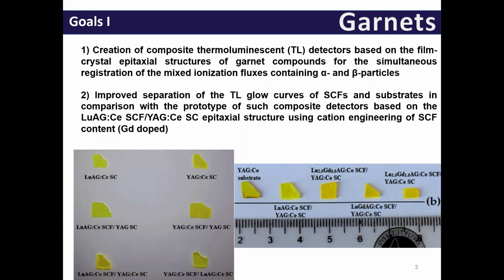The first part is about garnets. The goals are creation of composite thermoluminescent detectors based on the film crystal epitaxial structures of garnet compounds for the simultaneous registration of mixed ionizing fluxes containing alpha and beta particles. And the second goal is improved separation of TL glow curves of single crystal films and substrates in comparison with the prototype of such a composite detector based on lutetium aluminium garnet doped by cerium epitaxial structure, using cation engineering of the single crystal film content, and we use gadolinium doping for this part.